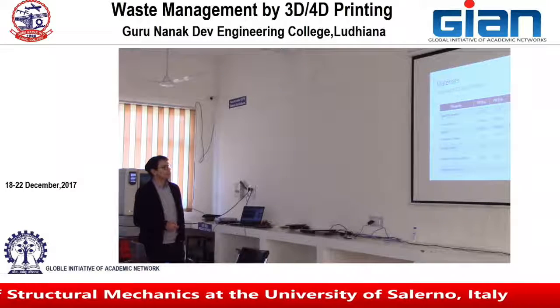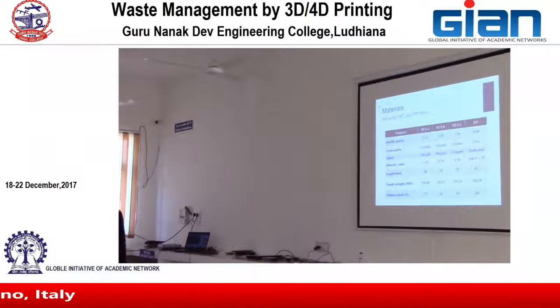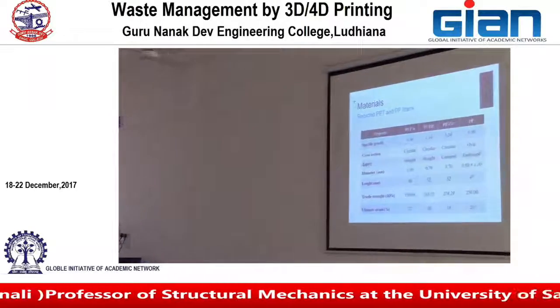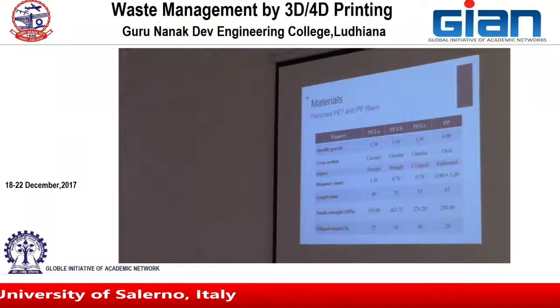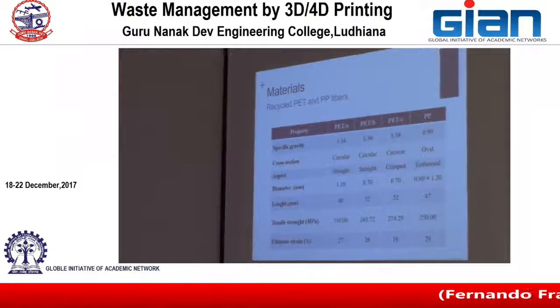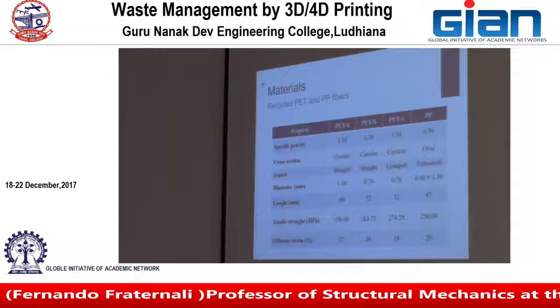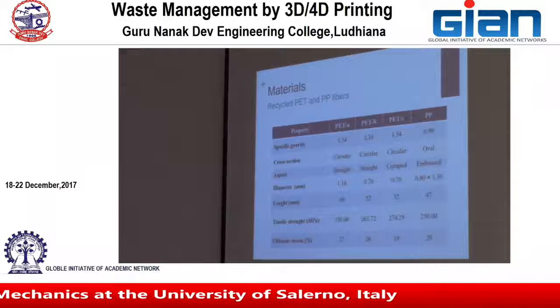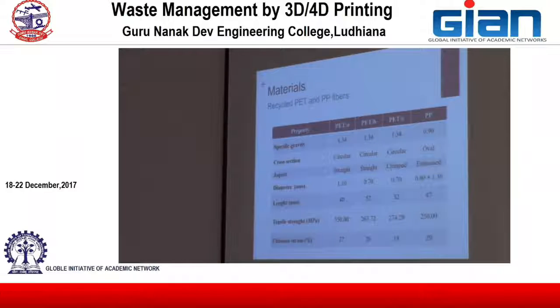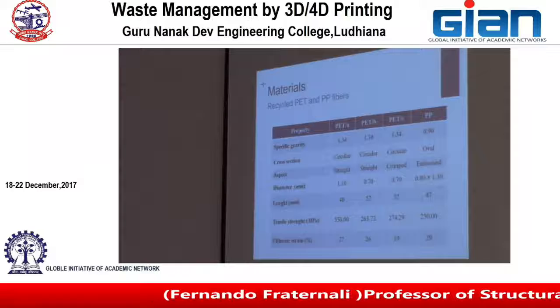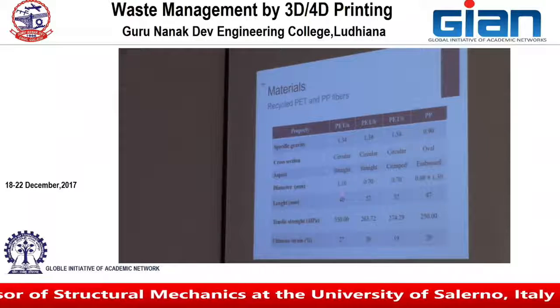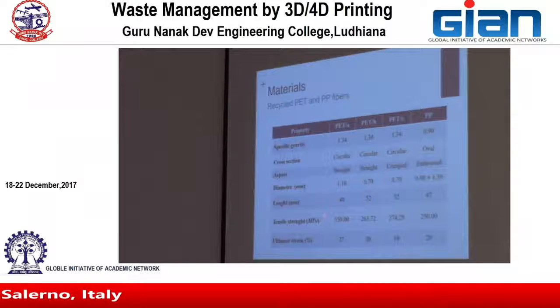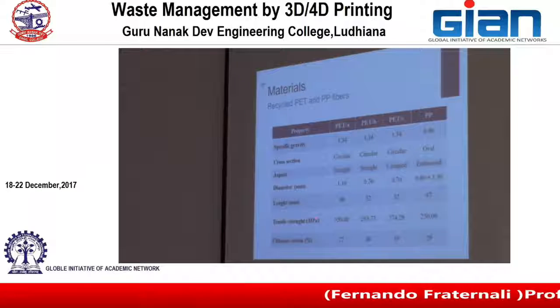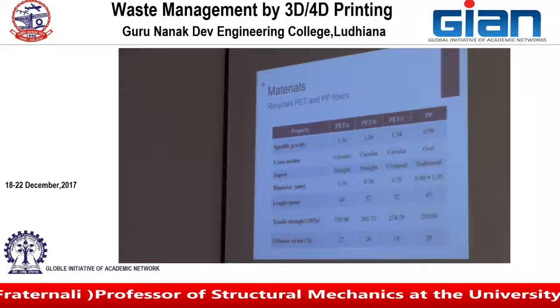And the fibers that we examined were of three kinds for the PET fibers, and one kind of PP fibers, polypropylene fibers. The PET fibers had circular cross-section and were straight or crimped, and those diameters are considerably thick because those fibers are intended to be mixed into a concrete, not a mortar. So the diameter is about 1 millimeter or 0.7 millimeters. The length is 40 millimeters, 52. Those are the values of tensile strength that we obtained for those fibers, which are different from each other depending on the process of extrusion.